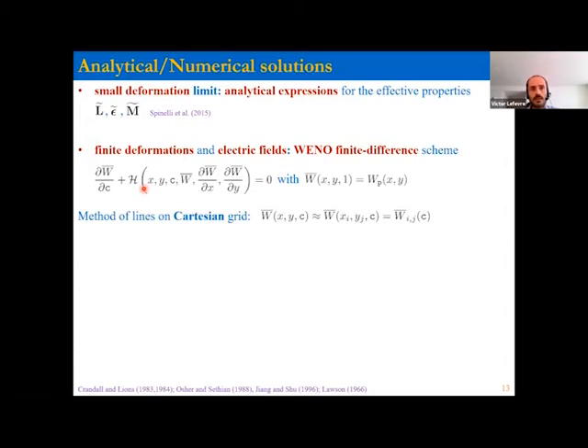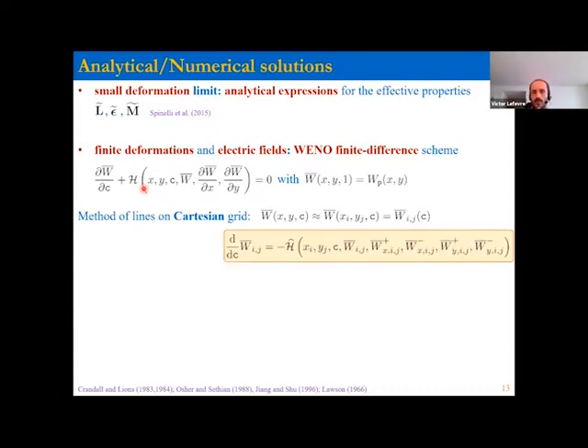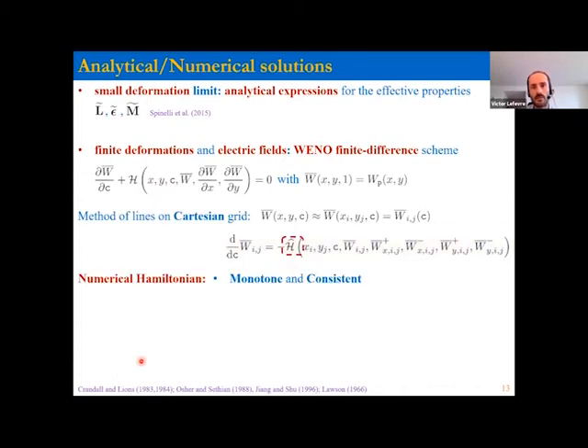So the idea is to discretize the space variable in a Cartesian grid and then compute approximations on the vertices of the Cartesian grid. Once you have the variables at the vertices, then you carry out the integration in time, in the fraction. That's the so-called method of lines. A lot of people have worked on schemes for these types of problems, including famous mathematicians. And they came up with a number of rules that your choice of scheme needs to satisfy if you want to converge to the viscosity solution.